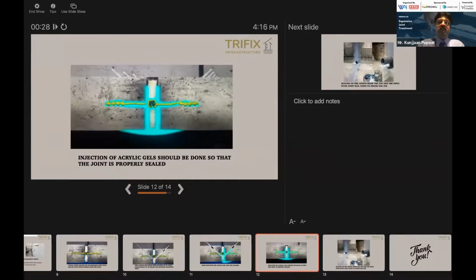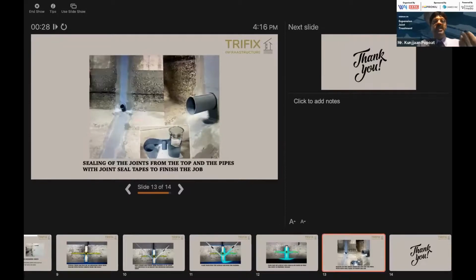The expansion joint was done in a perfect way, and after the expansion joint was done, we put the tapes on top of the expansion joint so that the water which is there in the reservoir doesn't leak through the expansion joints. And the injections we have done are basically to stop the water which is coming from the ground level into the tanks, and in fact the tank water needs to be pure water for some refinery works.